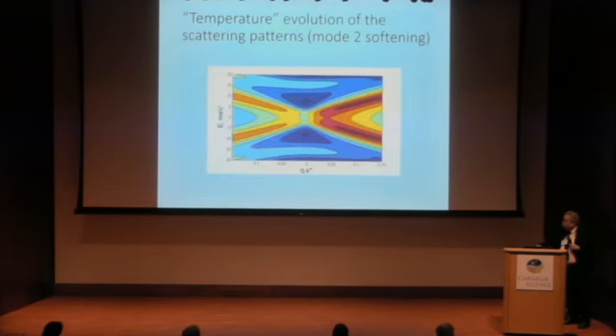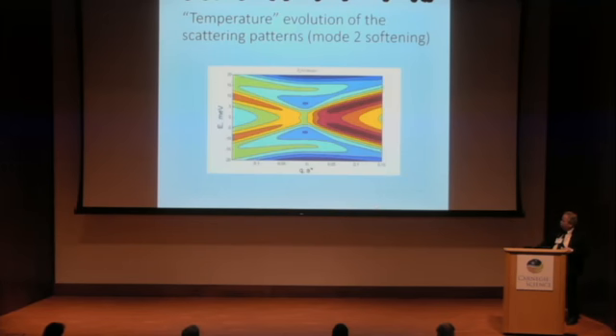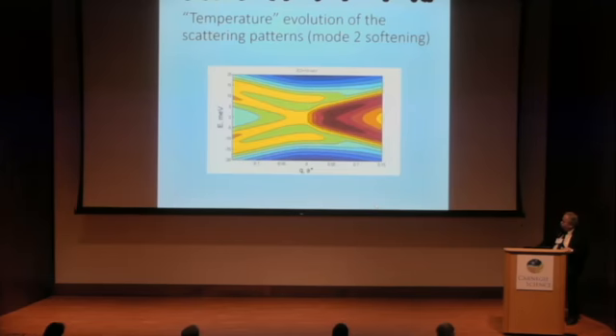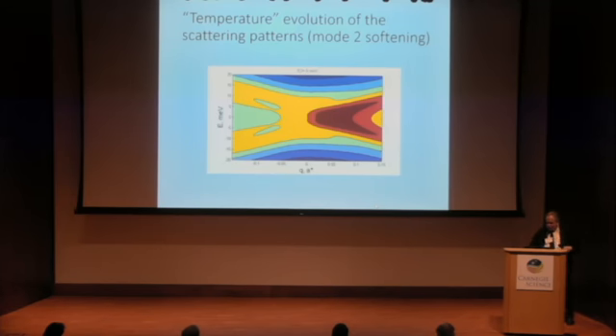Let's have a look at how it changes if we look now at S(Q,omega). It's a simulation, not modeling. No parameter is fitted; something arbitrary is taken to have something similar. We are far away from the critical temperature, so we have a nearly similar picture on the left-hand side and the right-hand side. Then the frequency of the second mode, let's consider that this one is the oxygen octahedral tilt, is going down, and the total scattering changes, and now we have a situation very similar to what I showed you in the experimental picture.